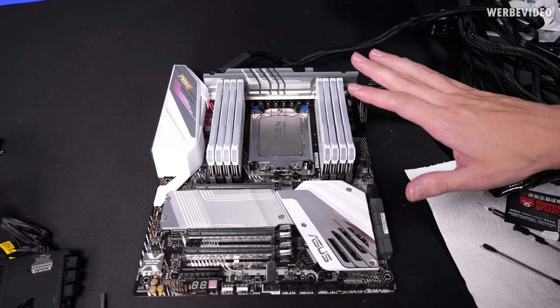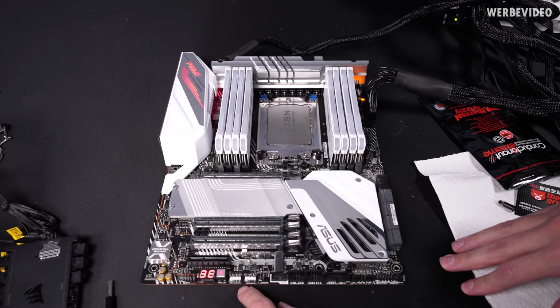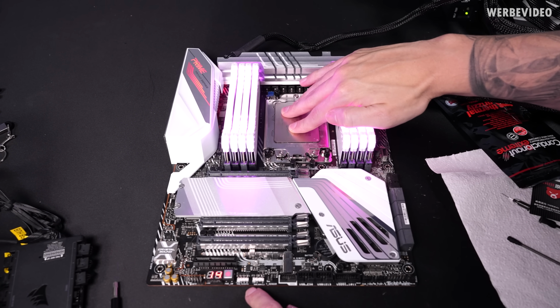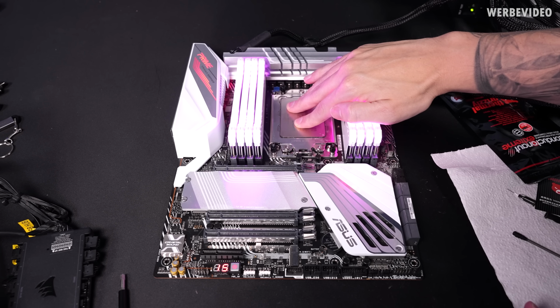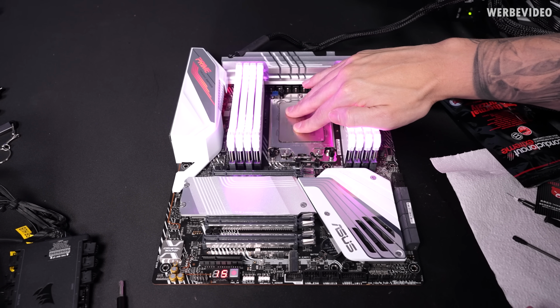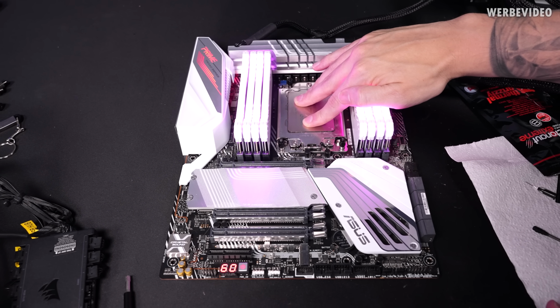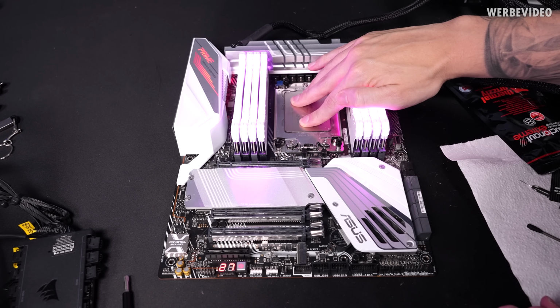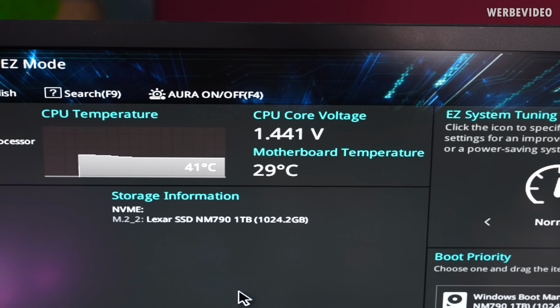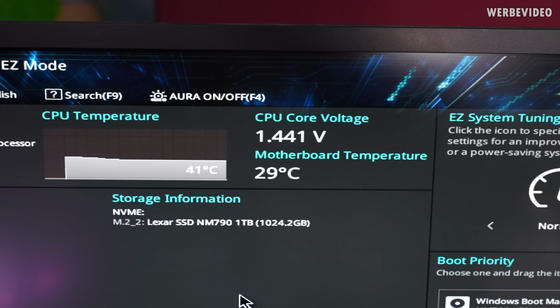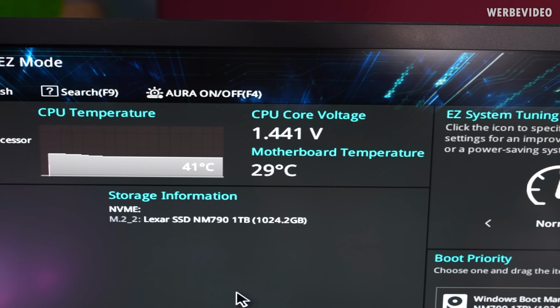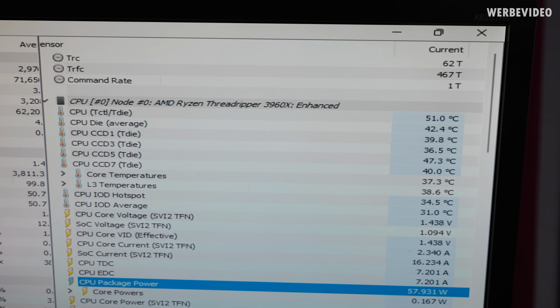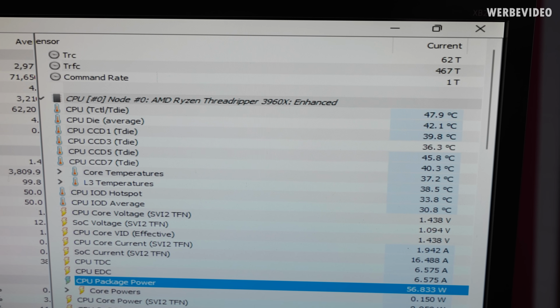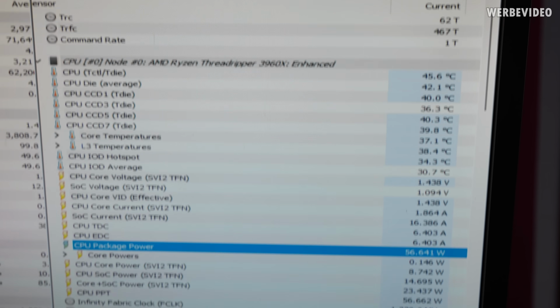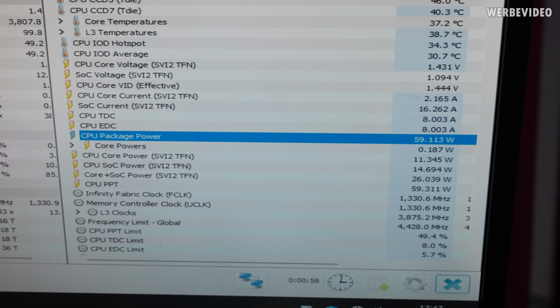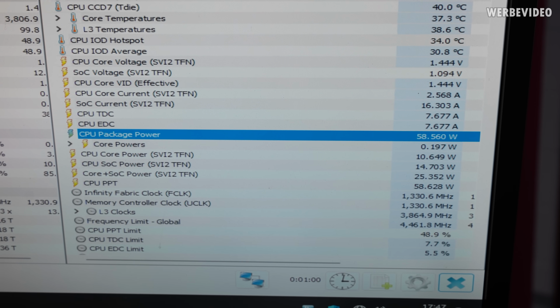Quick check to see if it boots. Seems okay, CPU is slowly getting warm. Yep. And now this looks a lot more promising. Previously, we would have seen like 80 degrees Celsius instantly. And even in Windows, it's a lot better, about 40 to 50 degrees Celsius in idle. And it also improved the CPU package power draw to like 50 to 60 watts.